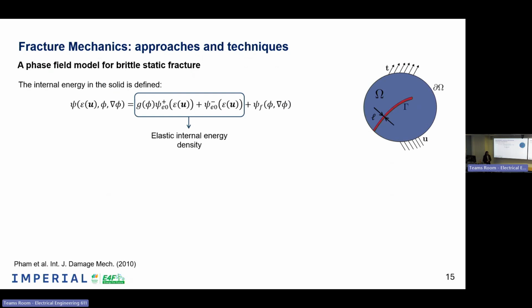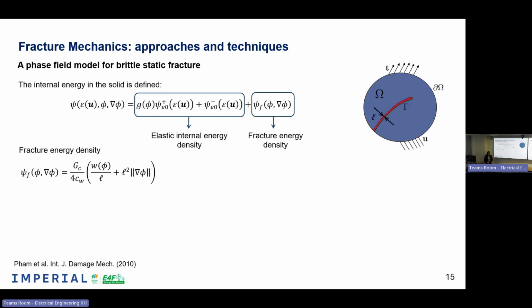The internal energy in the solid is defined as the sum of two different terms. One is the elastic internal energy density, that indeed it is the sum of another two different terms. You can see here, where you can see that these terms, they have a positive sign or a negative sign. This comes because we need to take into account the fact that only tensile strength are generating cracks. So if I do this, then the crack will be propagated or nucleated, but if I apply compression, we close the crack. So this must be taken into account somehow. And this is taken into account splitting the energy terms. And another term that is called the fracture energy density.